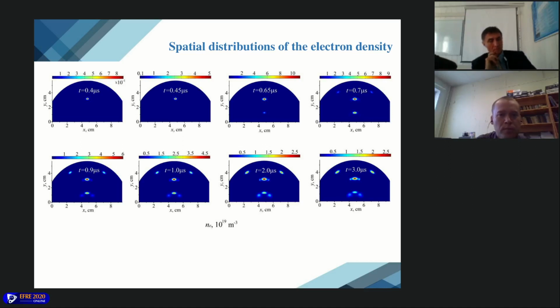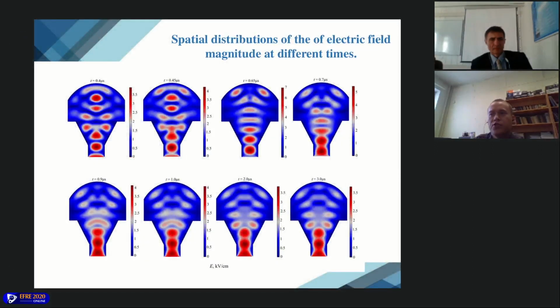and the critical density is proportional to the frequency squared plus elastic collision frequency. At the moment 0.45 microseconds, the electron density reaches the value 5 times 10 to the 19th per cubic meter, and at the moment 0.65 microseconds, the maximum value is 10 times 10 to the 19th for the entire duration of the microwave pulse. As a result of the formation of the first plasmoid, as can be seen from these figures, there is a spatial redistribution of the electric field.